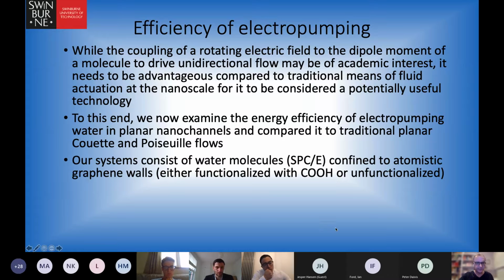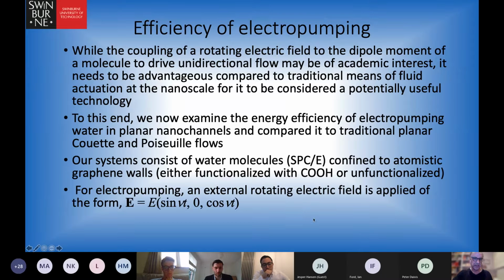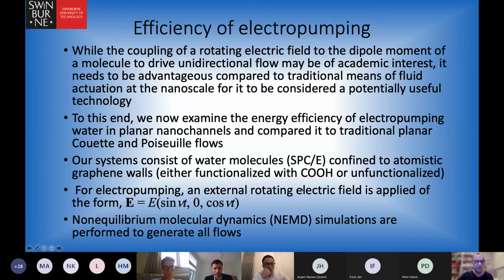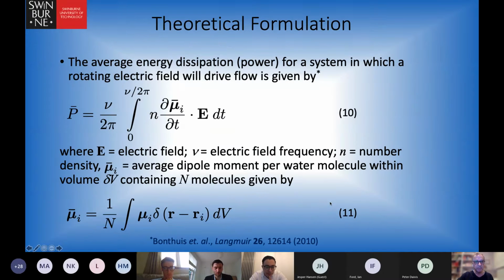The system that we look at is, again, a typical SPC/E water model confined between atomistic graphene walls, either functionalized or unfunctionalized. We apply a rotating electric field of this form, rotating in the XZ plane, and we perform NEMD simulations to generate all the flows and then calculate the efficiencies. So a little bit of theory. Back in 2010, Bonthuis and colleagues figured out what the theoretical energy dissipation, or power, for such a system driven by a rotating electric field would be, and they came up with this expression over here.